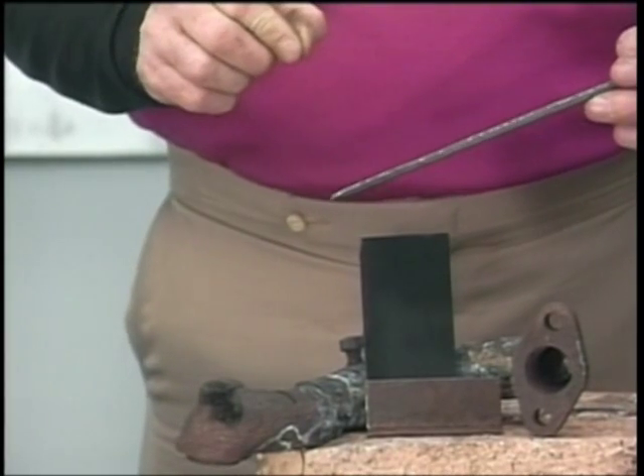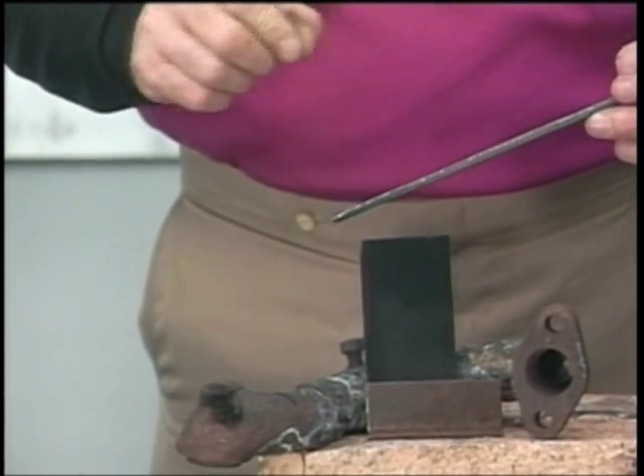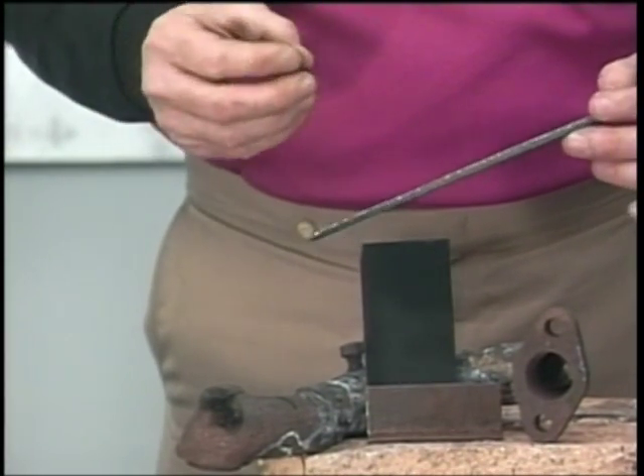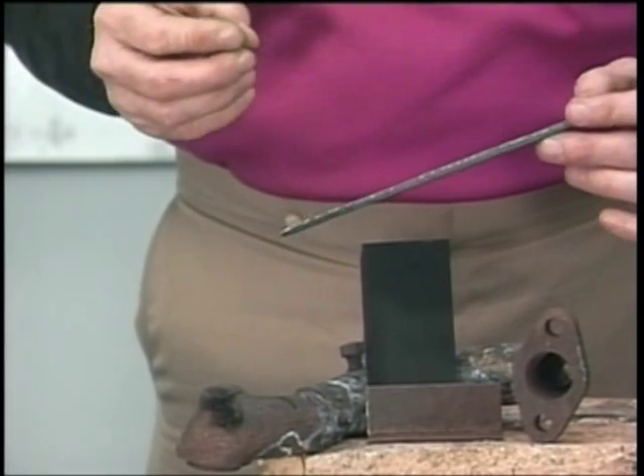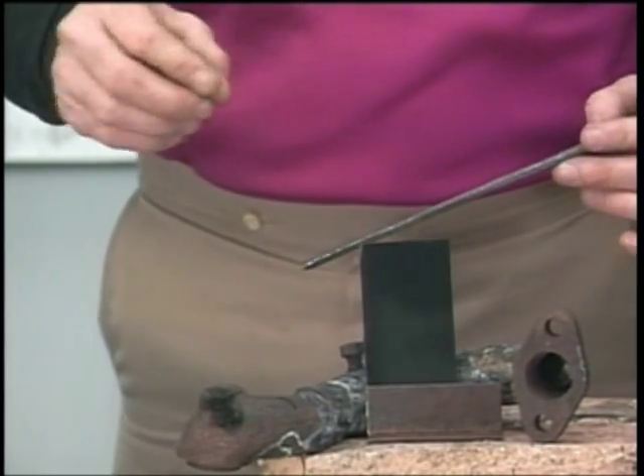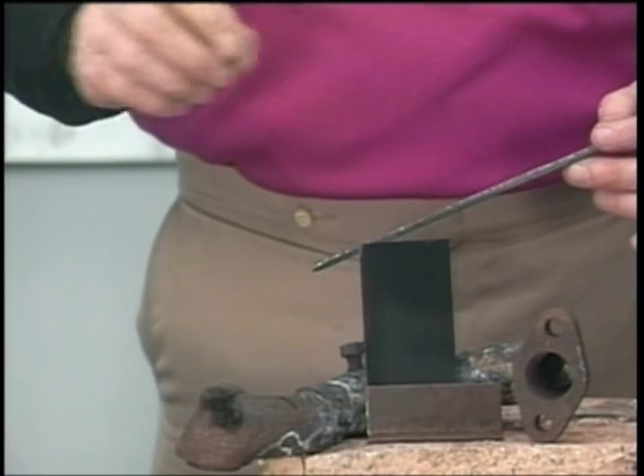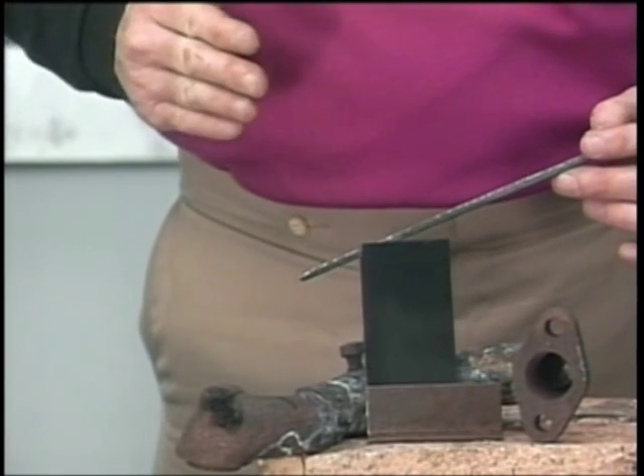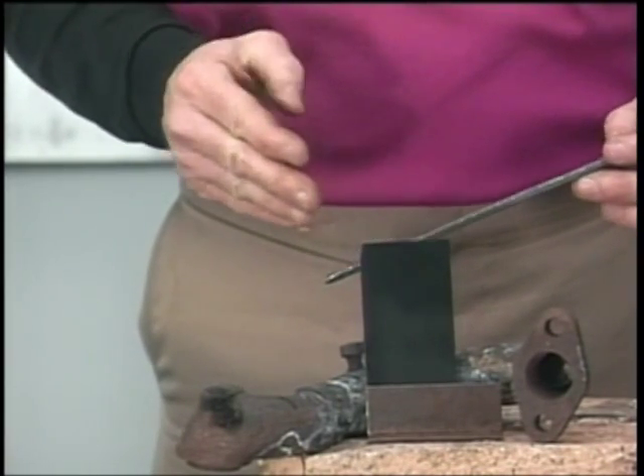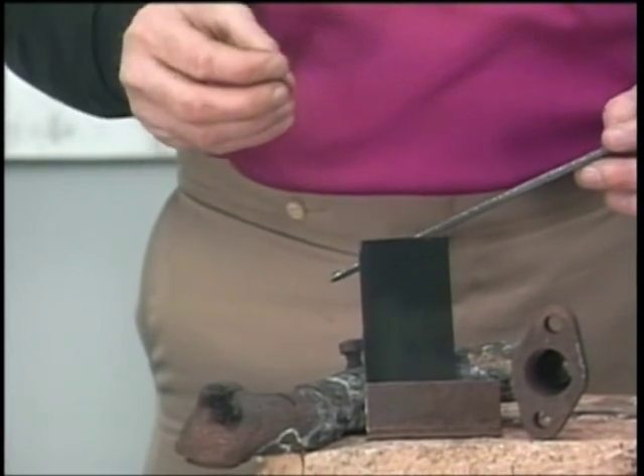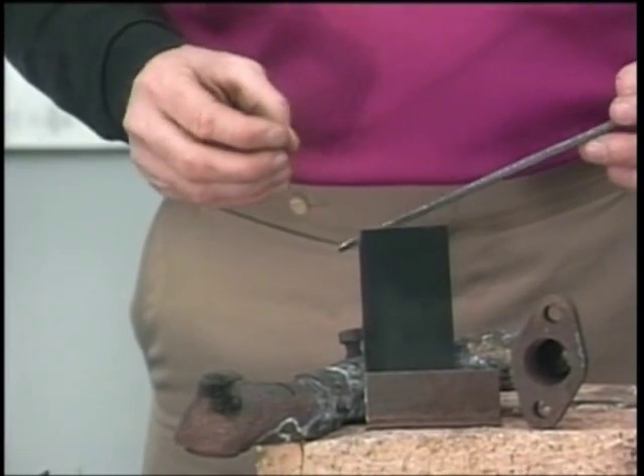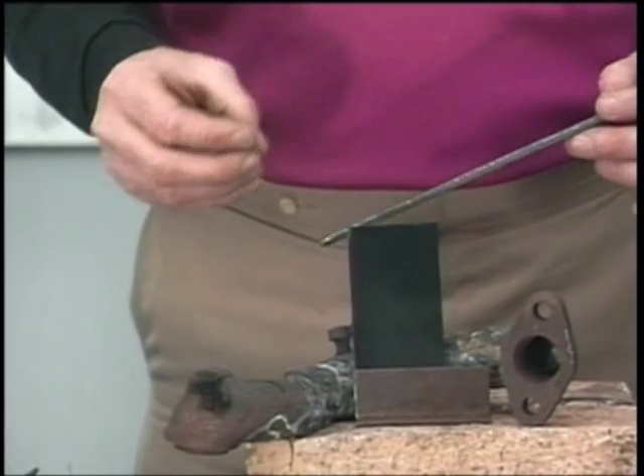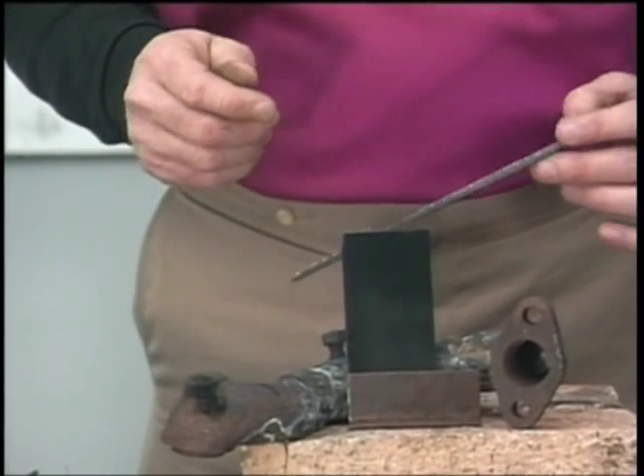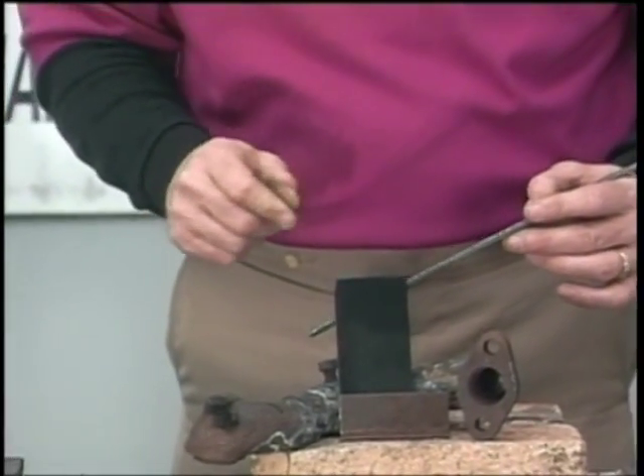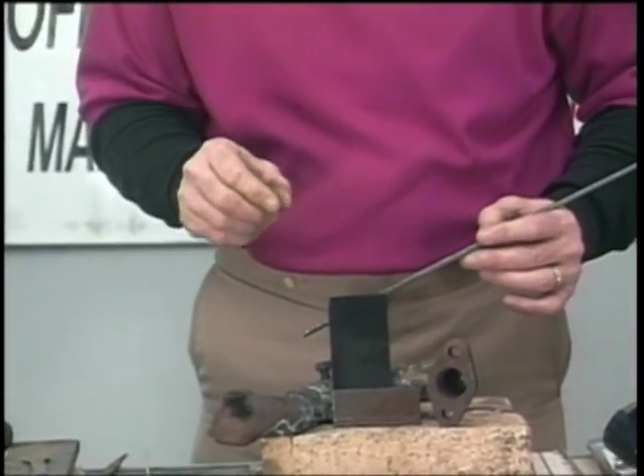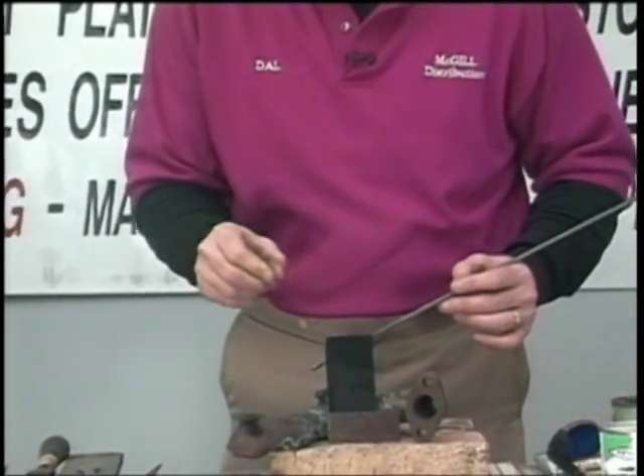The most important part on cast is coming back and post-heating it. Either stick it back in the oven, use your barbecue grill, stove, or whatever. If you don't have that, you'd have to come back with a torch and heat that whole part up real good, because allowing it to cool too fast causes most of the problems with your cast cracking. Now, if you're doing a real thick piece, if you don't have an oven or a grill, you're going to have to use a regular torch to go in there and heat it up and post-heat it, because our gun is so concentrated that it would take longer to heat it.